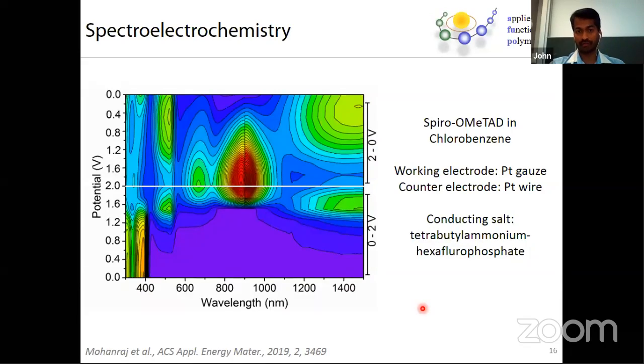For example, at the beginning, at 0 potential, the spiro has no other feature throughout the entire wavelength region except the ones corresponding to the neutral molecule. It has a band at around 300 nanometers. You would see in the next slides the normal 2D spectrum of spiro-OMeTAD. But with increasing potential, when you go up to around 1.2 volt, you start to see a new feature at around 520 nanometers, and at the same time some broad peaks around 1200 nanometers. These peaks probably correspond to the oxidized spiro species.